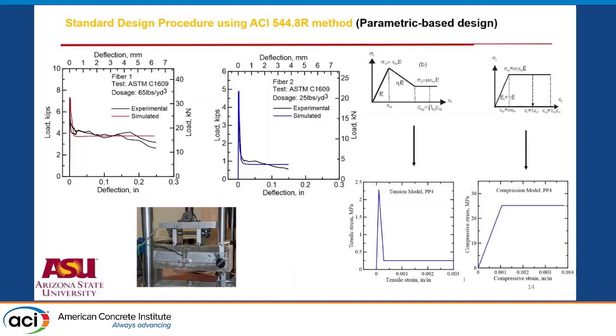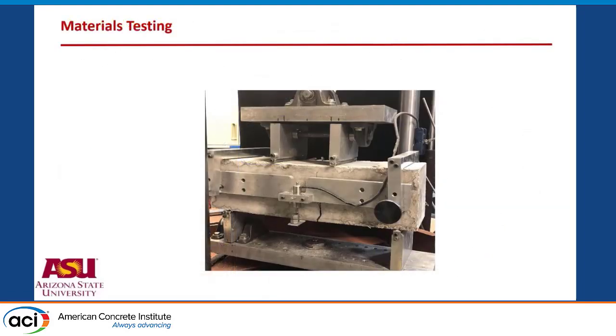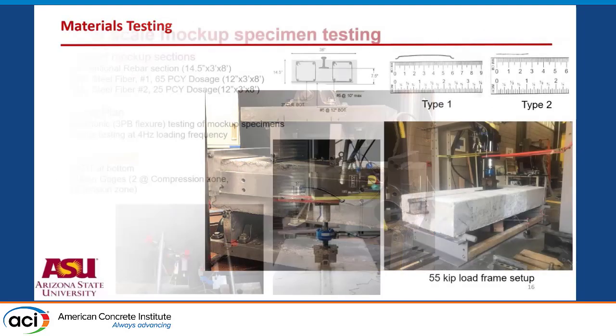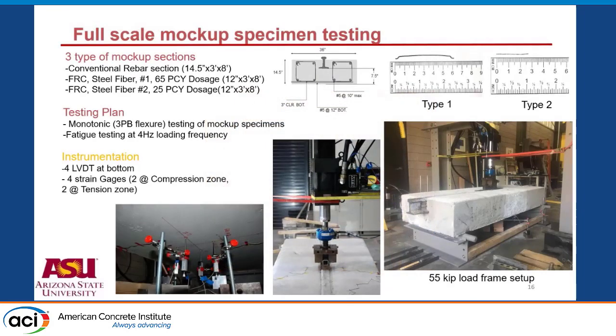So these are the 2 fiber systems that were provided. From the results, the flat part, which is the residual strength, is where your steel fiber is contributing to the response. Those are the 2 numbers that an engineer would need to take to do the calculations for long-term performance. We refer to it as residual tensile strength or equivalent flexural strength of the section. These are the preliminary tests done on these samples in accordance with the available standards. Now, the entire specimen is shown here, run as a 3-point bend specimen.